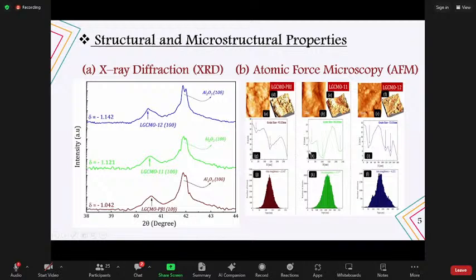Graphs G, H, and I show the grain size calculated using atomic force microscopy. From these three graphs, we can clearly see that the grain size decreases upon irradiation. That might be due to irradiation-induced local heating, as the ions impart some of their energy onto the surface, and that is why the grain size decreases. Graphs J, K, and L show the RMS roughness calculated from atomic force microscopy, and we can see that upon irradiation it increases. That is due to the higher fluence employed.